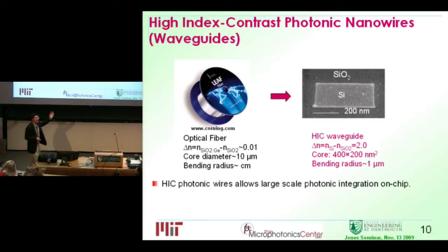You may wonder, silicon is obviously opaque to light. So why do you use it to transmit light? Actually, that's because we are using an infrared wavelength in which silicon is super transparent. It's more transparent than the regular glass in your window. So this will allow very low loss and very small dimension. You may also wonder that this one is still very thick. This is about 400 nanometers, while we have electric wire of only 45, so why is this one more powerful? Don't forget, we can put thousands of wavelengths in this single waveguide. So if you divide the width, each channel is 0.4 nanometers. Okay? That's about the lattice constant of a material. That level is very, very hard to achieve with an electronic approach.